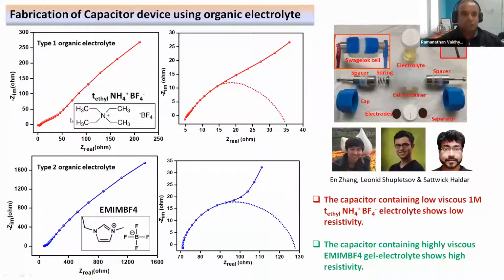This is where we joined hands with Professor Stefan Kaskel. These are the PhD student and master student from their group, and Satvik, who is a postdoc with Stefan, conducted this study along with them. So what we have gone on to do is we have used ionic liquids as the electrolytes now. And ionic liquids can give you a much higher stability to your applied potential, which means you can start investigating a wider potential window. And we chose two different ionic liquids. One is less viscous, one is highly viscous. And immediately we saw that the less viscous ionic liquid is able to give you less resistance compared to the bulky ionic liquid. So we stuck to this for most of the measurements.